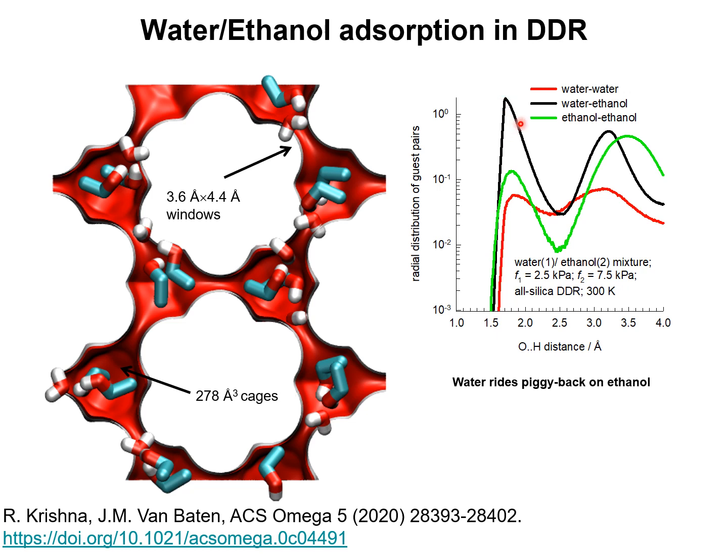In other words, the water that is bound with the ethanol molecule gets adsorbed by riding piggyback, and this leads to an enhanced ingress of water into DDR zeolite.